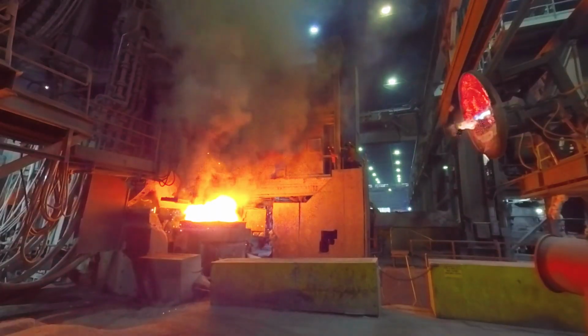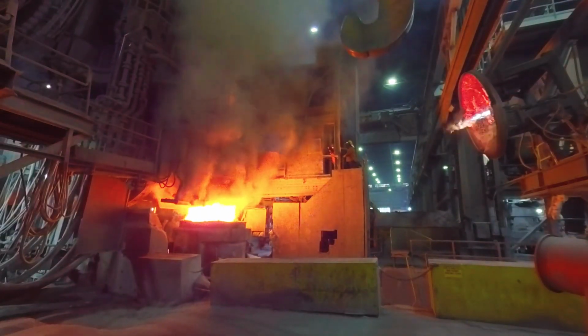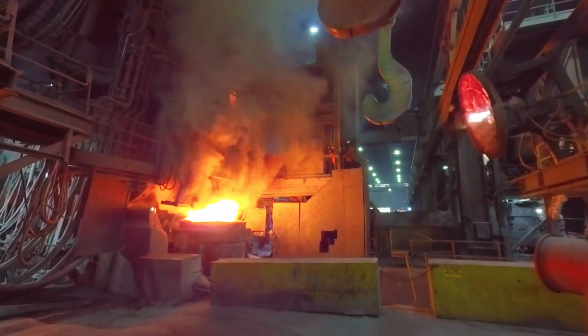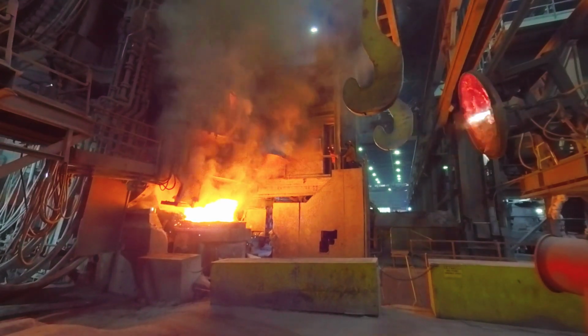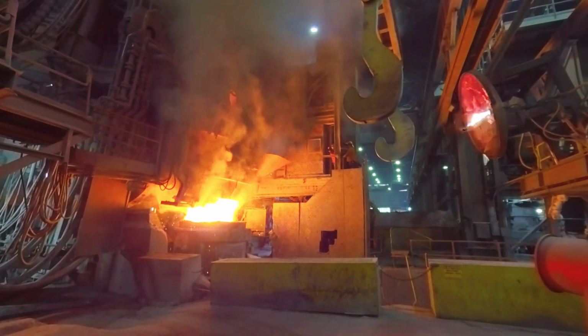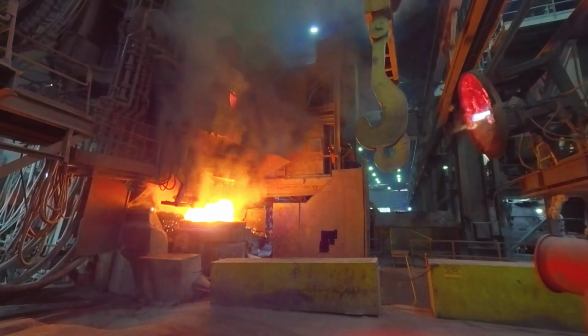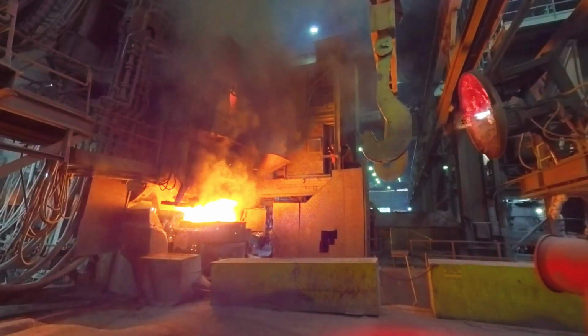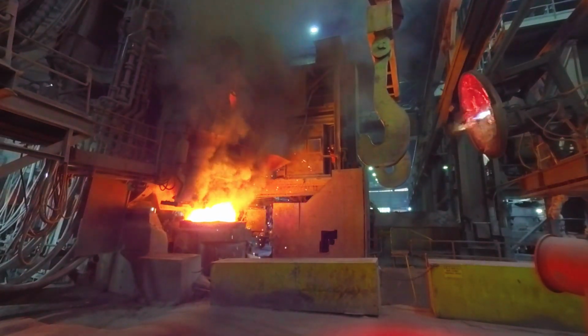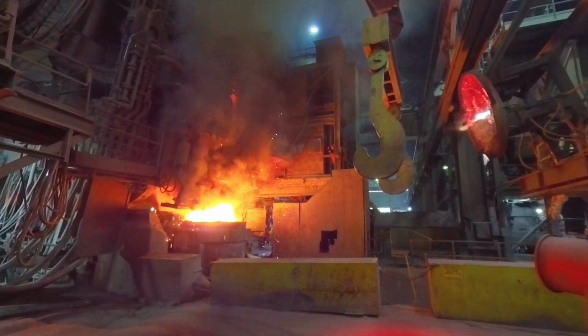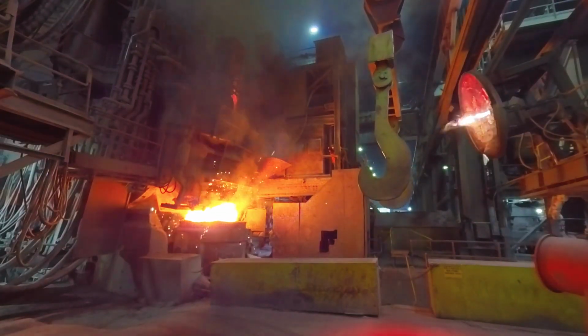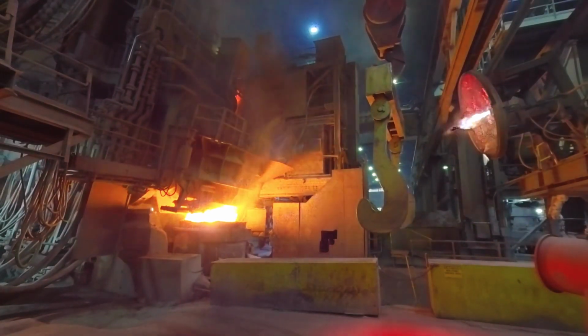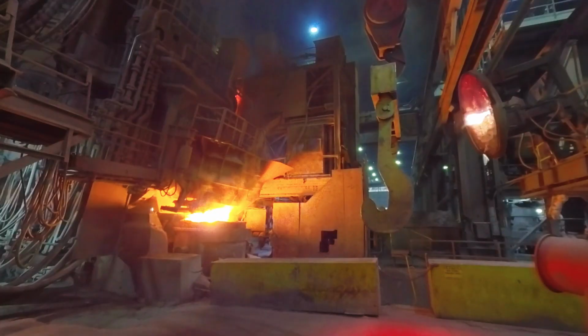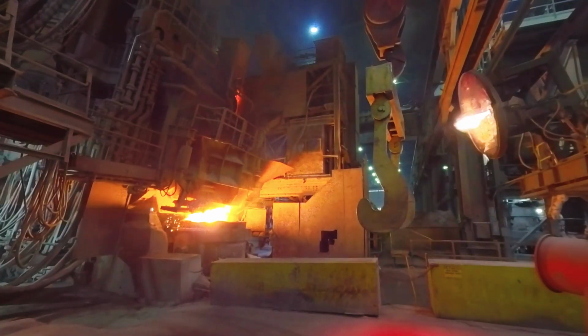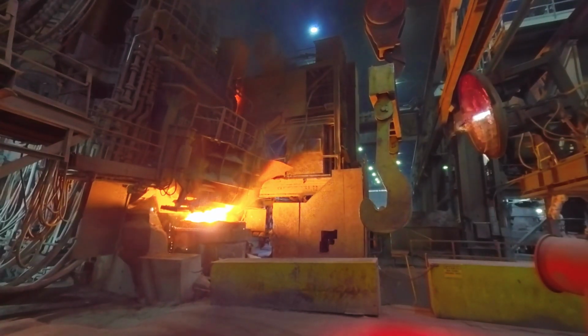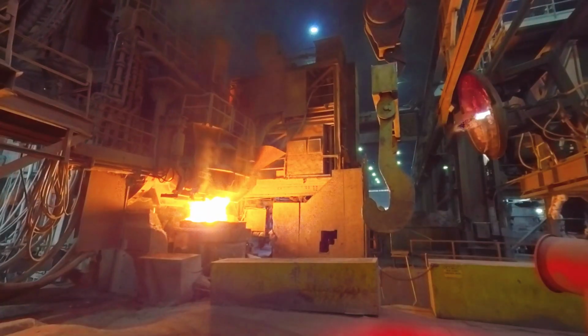But the goal is precision. Inside the furnace, molten steel sits beneath a layer of slag. As the furnace tilts, operators carefully control the flow, keeping the steel moving out while leaving the slag behind. It works much like a separator, allowing the clean metal to flow while impurities remain in the furnace. Once the correct weight is reached, the furnace quickly tilts back.